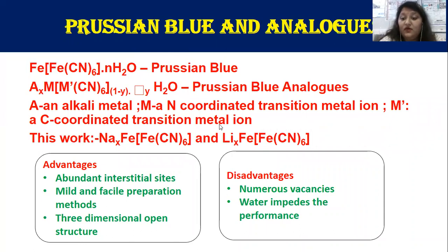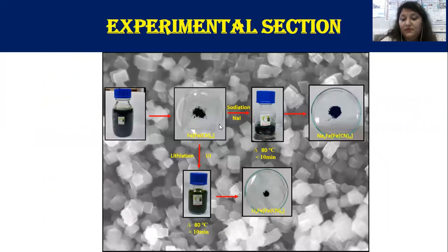The sizable framework of these Prussian blue analogs allows cations to diffuse through the interstitial sites. Ease of synthesis, tunability of structural development, as well as higher theoretical capacity due to the redox centers are added advantages of Prussian blue analogs. However, the major drawback can be attributed to the coordinated water, which leads to lower utilization of theoretical capacity. So substantial efforts have been made to develop Prussian blue analogs without these issues by metal substitution, dehydration, surface coating, etc.